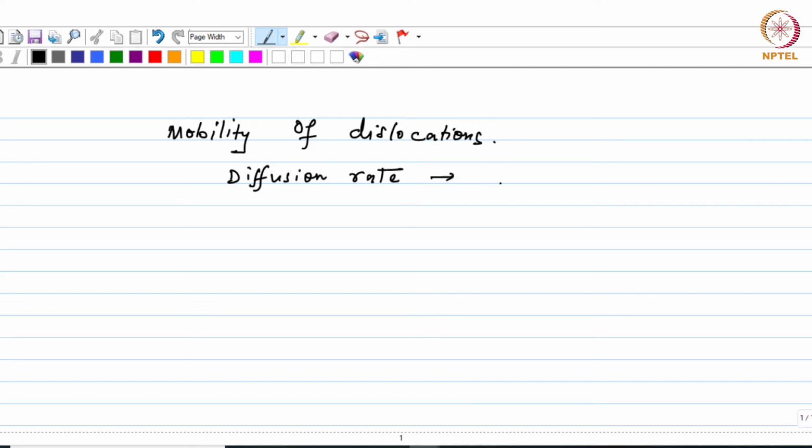So now at temperatures at which the diffusion rates are high enough, the solute atoms will quickly move to the dislocations, and if they have mutual attractions, then a second phase may precipitate at the dislocations.